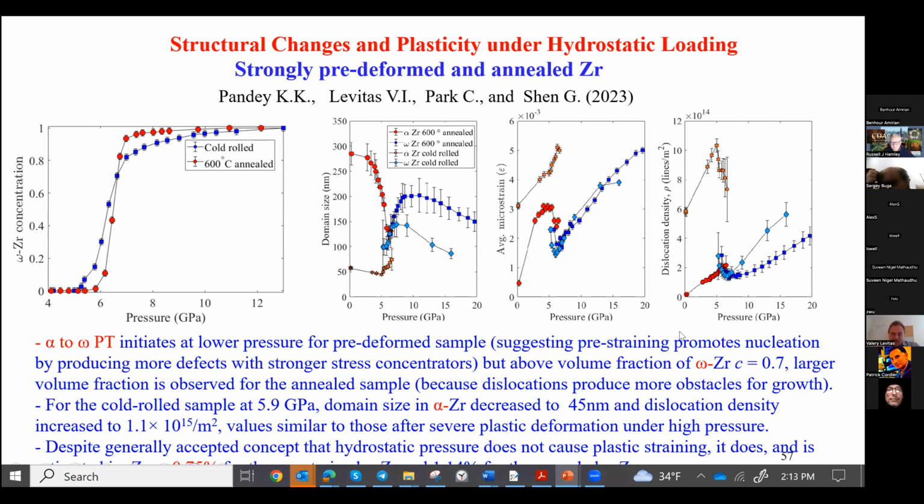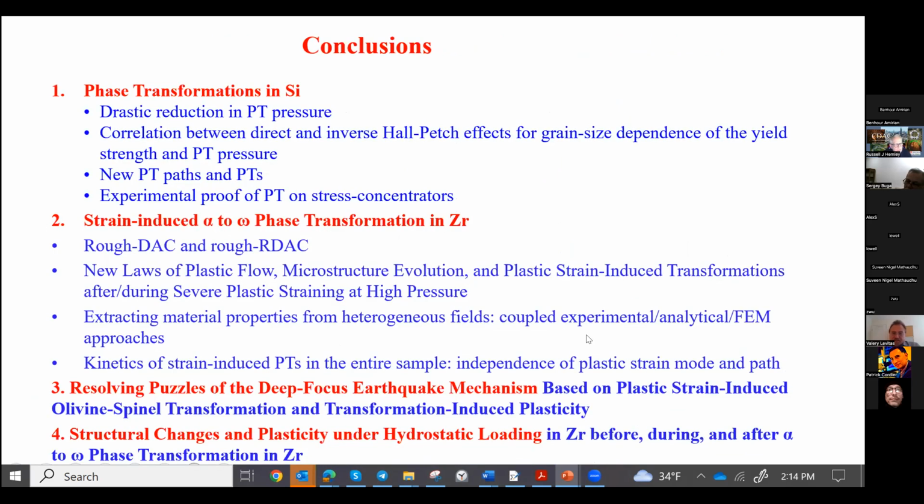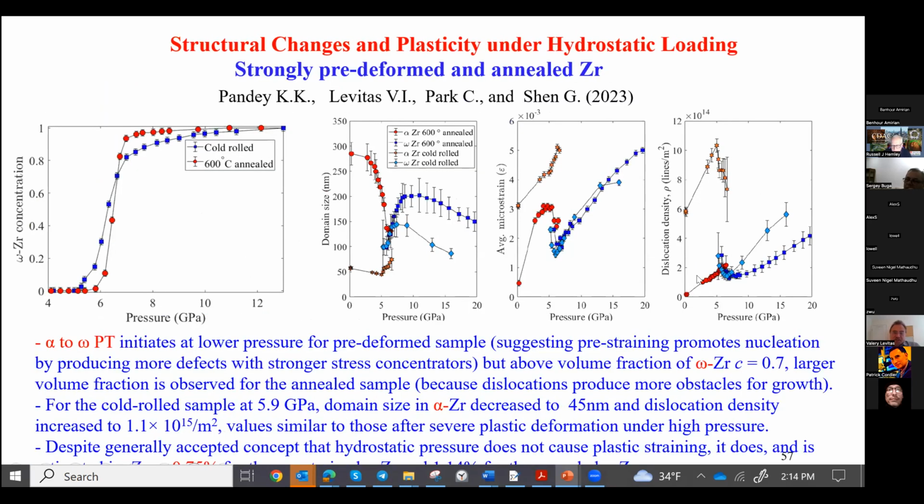And here it is even larger for annealed material, and it is clear that the change in dislocation structure is larger because the yield strength is lower. So there is more significant plastic strain, and this comes from grain boundaries and triple junctions, from the heterogeneous orientation of grains. Then it develops internal dislocation structure, and all this change in dislocation structure is plasticity. Yeah, I agree.